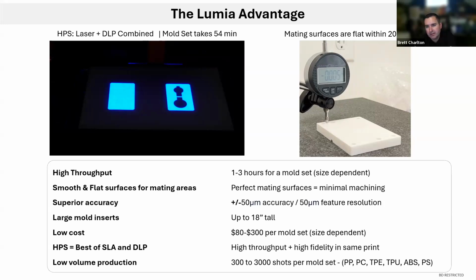Historically, we've had to add stock to the parting lines and back surfaces and potentially even other surfaces and make other allowances that we would then machine away to achieve the appropriate stack height and fitment. With the Axtra3D system, we've been able to eliminate most of these secondary allowances as they are no longer necessary and only add time and cost to the process. As mentioned before, we have gone fairly large with our concept mold inserts, but we haven't even harnessed the full capacity. The system has the ability to print up to 5 inches by 10 inches in the X and Y directions, and the full depth of the chamber is 18 inches, which should significantly satisfy a large size constraint.